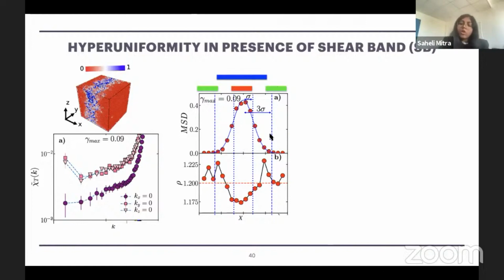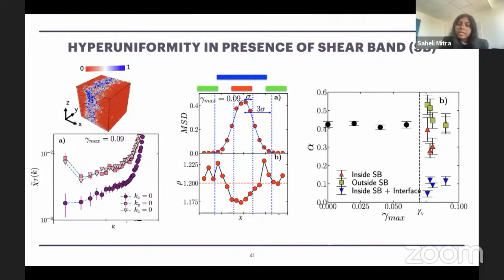When we do so, we compute the number density variance and extract the hyperuniformity index, the hyperuniformity exponent alpha. We see that below yielding, when there is no shear band, of course my system is hyperuniform in the absorbing states. And above yielding, the parts outside of the shear band and the parts inside of the shear band still continue to be hyperuniform. And we lose the hyperuniformity when we include the interface between these two regimes.